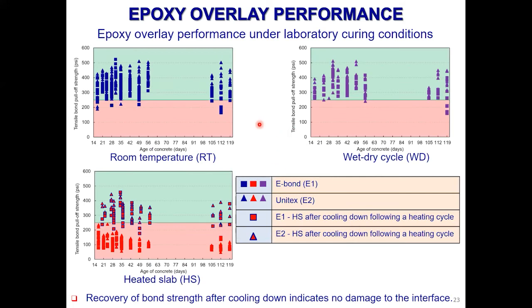When we look at overall results, irrespective of the overlay type, epoxy type, as well as the concrete, you can see under room temperature, strength is greater than 250. This is the mark for 250. Even if we subject it to wet and dry cycles with sodium chloride, still the bond strength is not compromised.